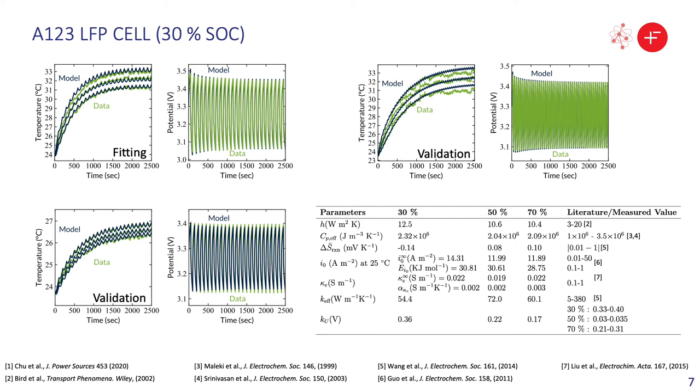The experimental data was fed in and COMSOL with MATLAB iteratively tested parameter values until the simulation output matched with what was given to it. The parameters needed for that match is shown in the bottom right. And we used those parameters to then simulate different square waves as a validation.